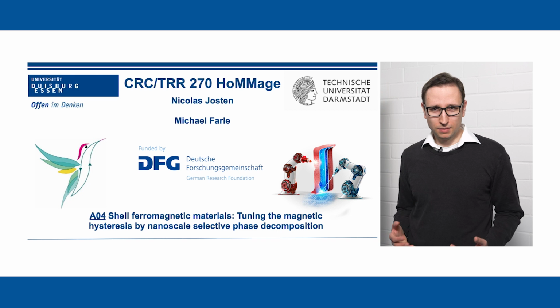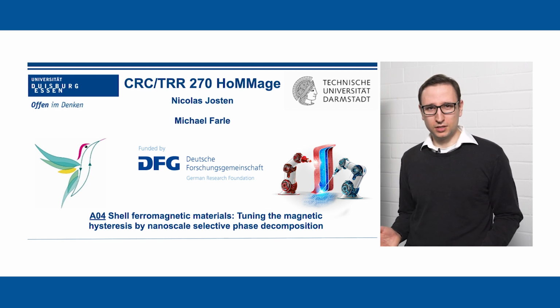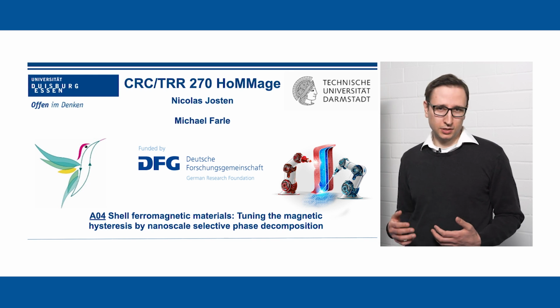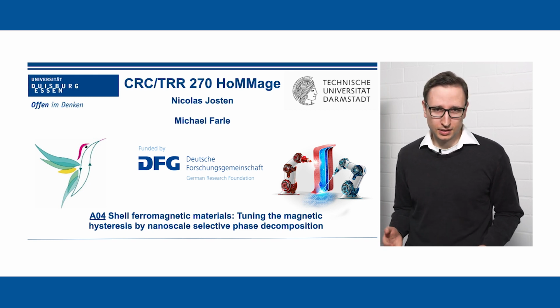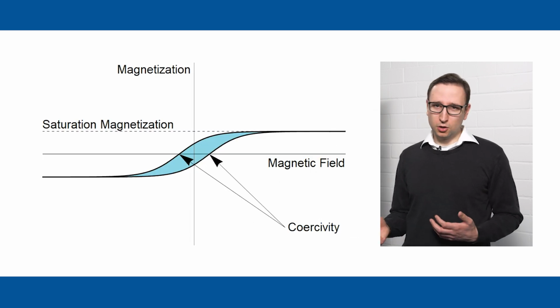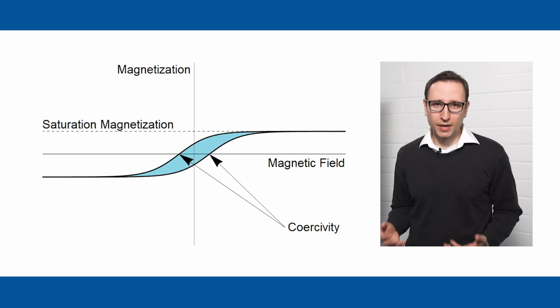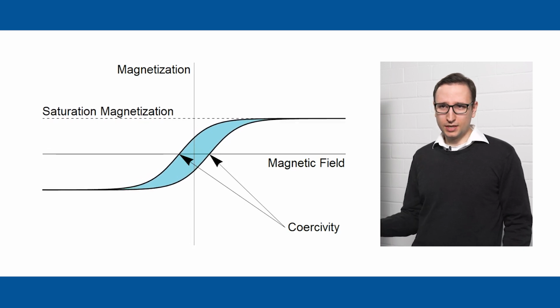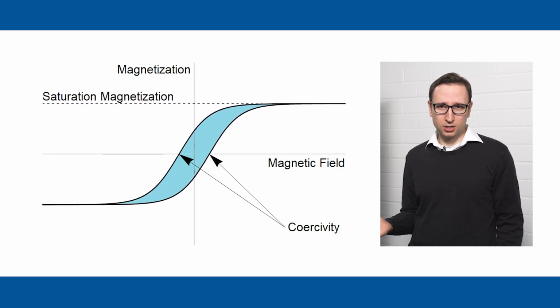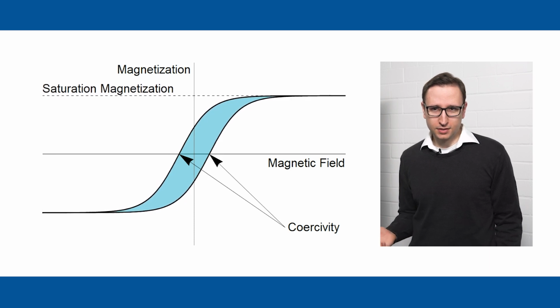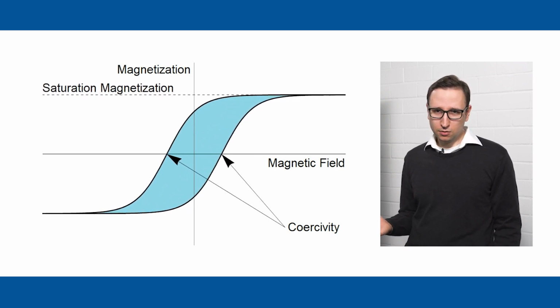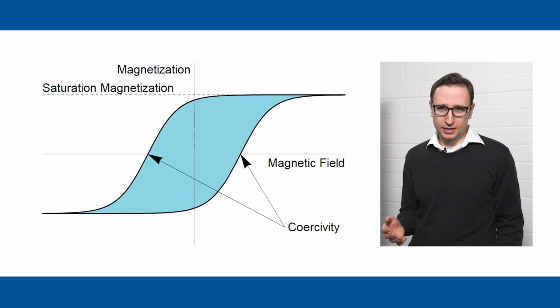Hi, I'm Nicolas, a PhD student in the CRC 270 HoMMage. My project is A04, Shell Ferromagnetic Materials, tuning the magnetic hysteresis by nanoscale selective phase decomposition. The goal is to optimize the properties of permanent magnets. This can either be done by increasing the total magnetization, so to say the strength of the magnet, or by increasing the coercivity, which is the resilience of the magnet against external magnetic fields. The samples investigated in my project, for example, have a surprisingly large coercivity.